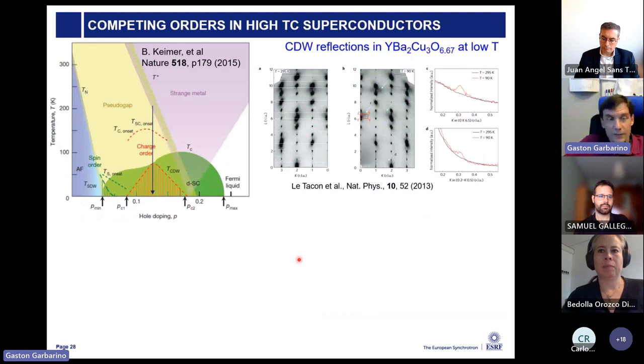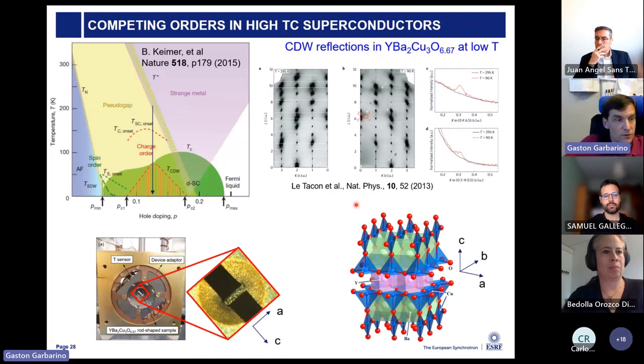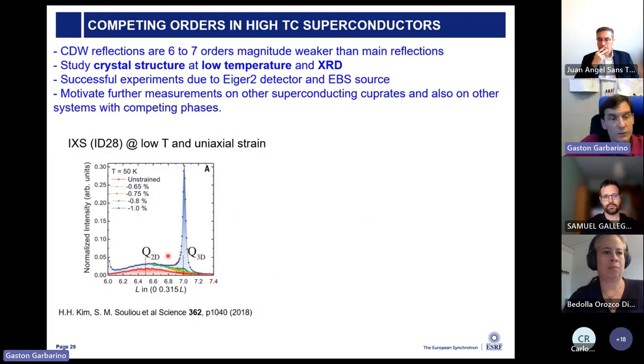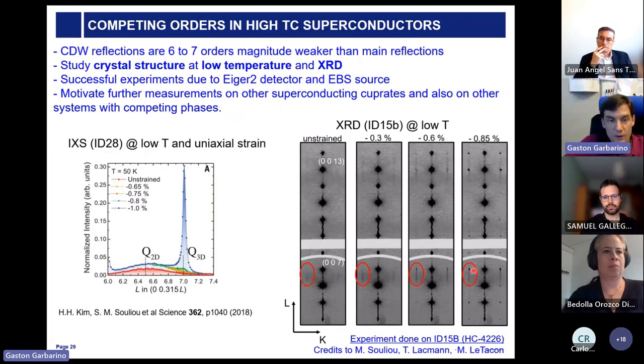At the same time, now we have a very intense beam and also a very powerful detector in terms of dynamic range. So we are able, for example, to study in YBCO, yttrium barium copper oxide, a high-Tc superconductor, the appearance of this charge density wave associated with the pseudogap that was already mentioned to exist in this particular region of the phase diagram of these cuprates. And we are able to solve at the same time the full structure of the sample. If you apply some strain, you can induce a change from a 2D charge density wave to a much more 3D one, in which you see that the peak is now well defined.